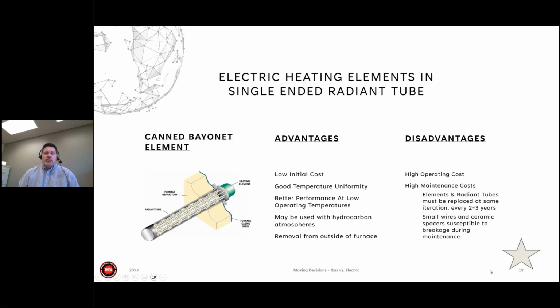So the electric heating elements inside of a radiant tube would be put inside of a single-ended radiant tube like the gas heated system, so they can be applied in the same type of form as the gas-fired radiant tubes. So this might be an option for retrofitting if you had single-ended gas-fired radiant tubes. These have low initial costs and good temperature uniformity, and they actually perform better compared to gas at lower temperatures.